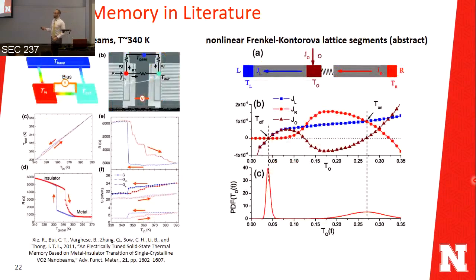In the literature, people tried to introduce thermal memory using vanadium dioxide, which is a material that can convert between dielectric and metal around 340 kelvins. The problem with this is that it has a fixed operating temperature. You can achieve a memory only around this temperature. The second attempt was very abstract. It was just theoretical work using two chains of molecules connected with a central molecule with nonlinear force. It's very abstract, and it's not applicable in the near future.